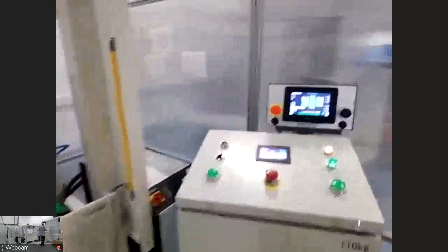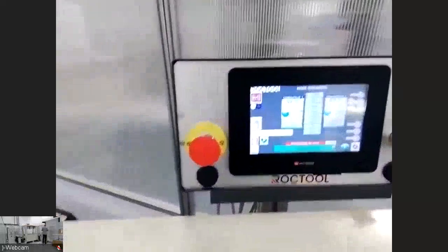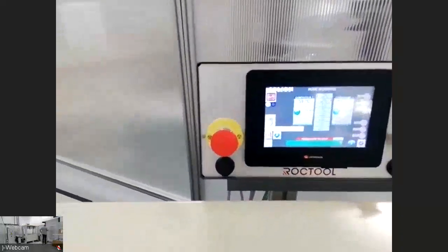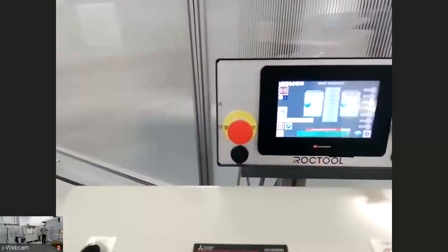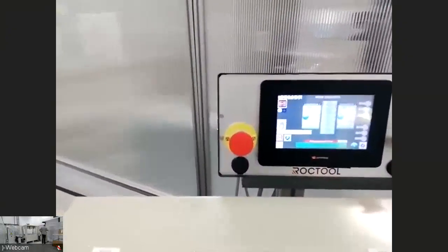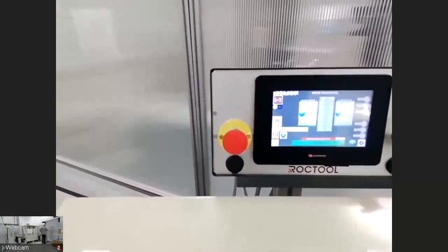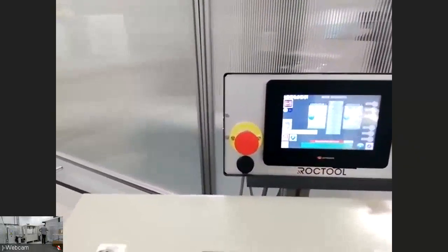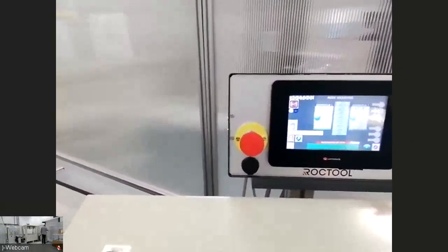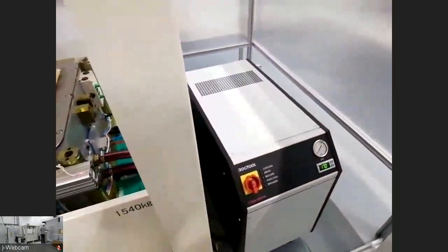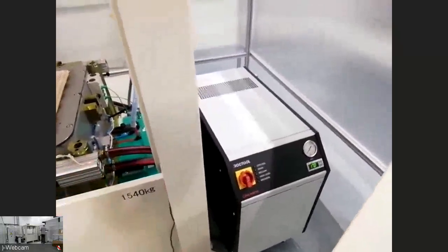On the right of these cells, we have the interface controller. Here it's the process system, where we can manage and set up all the process. We can manage, of course, the heating, holding, and cooling ramps, with the indication of the power we set up in the process. We have the information about temperature and time, of course. On the right of the cell, we have the mold cooling unit. We use it, of course, to cool the tool during the cycle.